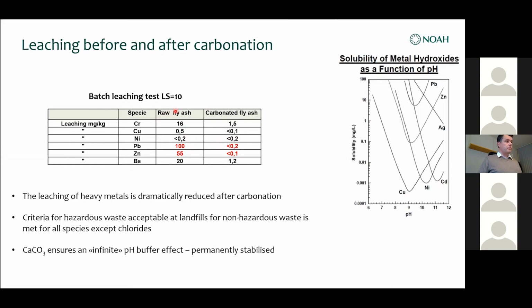The other favorable thing about carbonation of fly ash is that you produce a lot of calcium carbonate. If you have calcium carbonate in water, the pH is between 9.2 and 9.5, and you have a lot of buffer effect. I know this is very simplified, but it represents what we observe. For lead, zinc, and copper, which are the main problems for fly ash, the minimum leaching of their hydroxides is at around pH 9 to 10, which is spot on what you get when you add calcium carbonate in water. So it's a very robust system, and you will have long-term control of the pH over long periods of time.